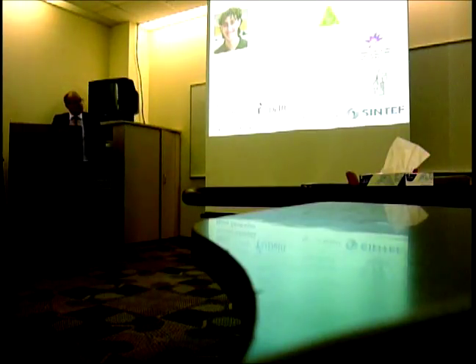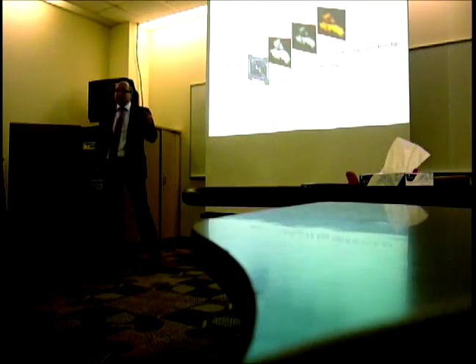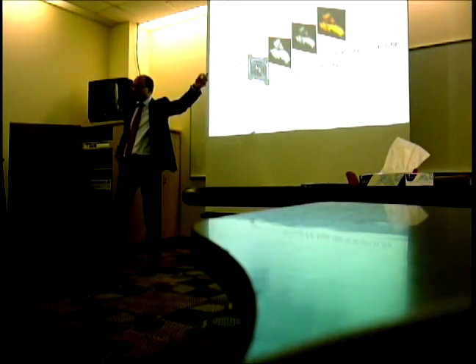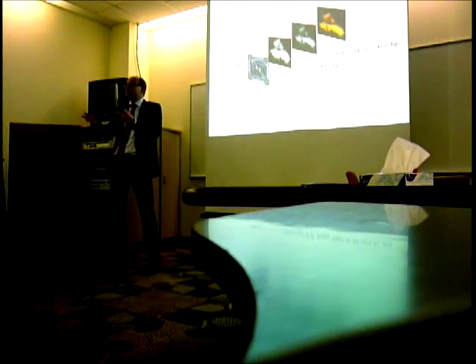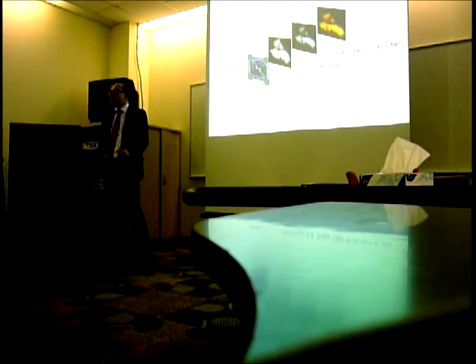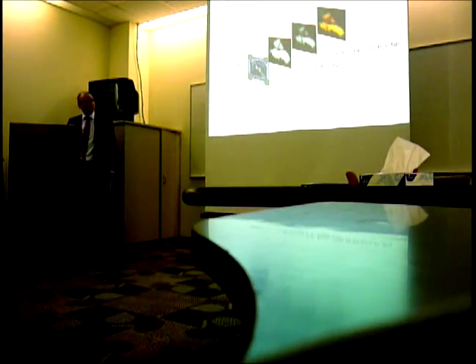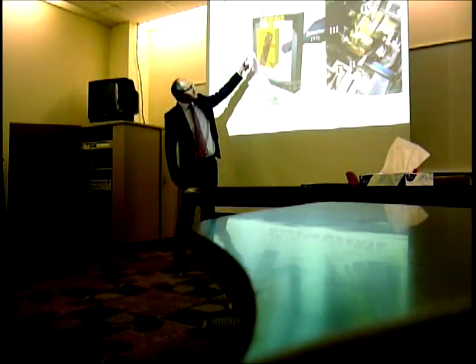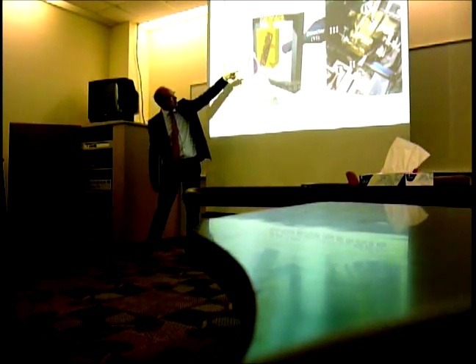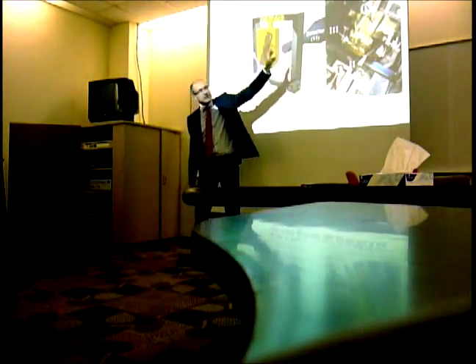Now you can ask yourself, Bert, but these are big zeolite crystals. Can we transfer this to the small scale? And I have to thank Luis Aramburo, who will soon finish his PhD. Back to X-ray microscopy, where I started. I showed you X-ray microscopy. You can do also X-ray microscopy on zeolite and measure aluminium and even carbon. So we can now measure carbon deposits. For this we developed a few years ago an in situ cell for soft X-ray microscopy. So the X-rays are going through the cell, and you analyze it.